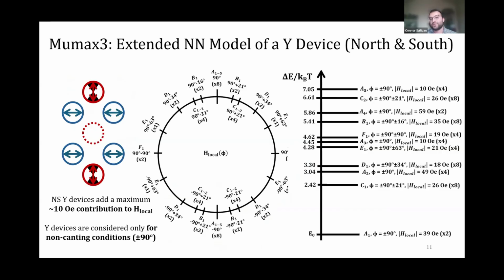We're also able to develop their energetic states. So we're actually able to observe what these spin configurations actually are. And when we do so, we can pick out which ones are or are not monopoles based on the simple definition that a sum of charge should be 0 about a node. And it turns out these double nodes always have some non-zero charge about them. The red here being cases in which they're considered perfect monopoles, and these purple ones being monopole-like, so they're EMM-like states.